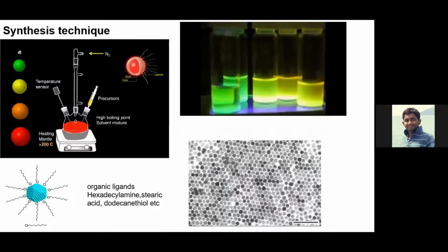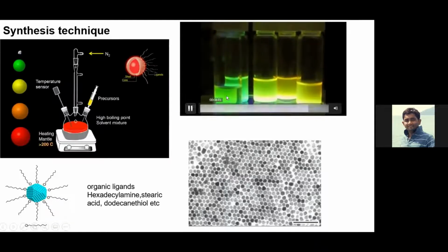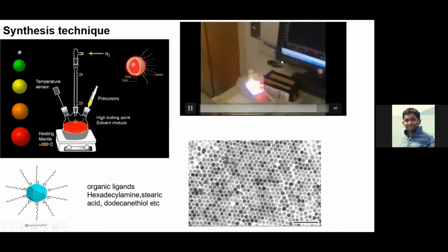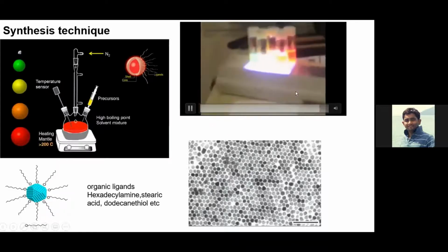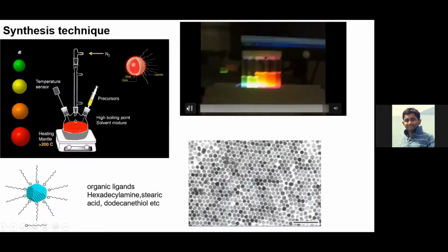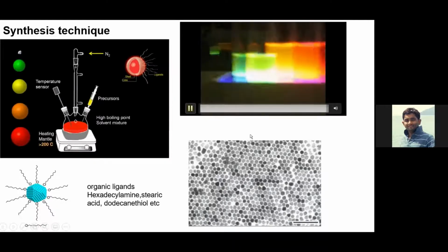Now you see under UV light, it shows blue, green, yellow, and you can also see the red, orange in the same pot of reaction. This is the best part of these quantum dots: in only one single reaction you can have full colors, from violet to red, that you can control. And you see the particles. These are the nanocrystals.